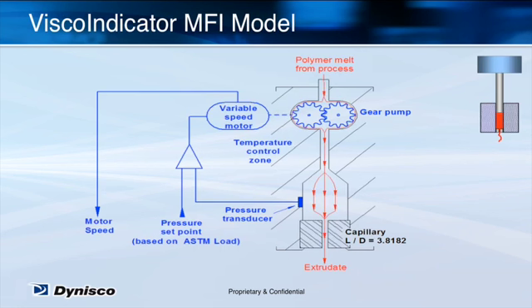Melt flow indexers must be hand-loaded with pellets and weights to create shear conditions, so the test requires a technician and must be done offline. The ViscoIndicator simulates both the apparatus and test conditions of the MFI test right on an extruder.